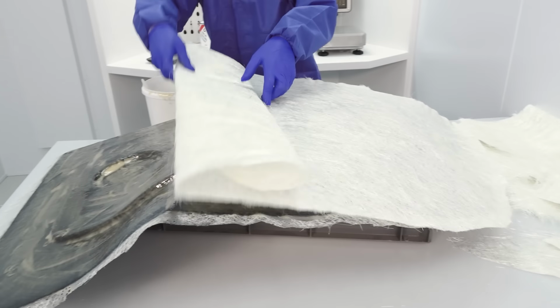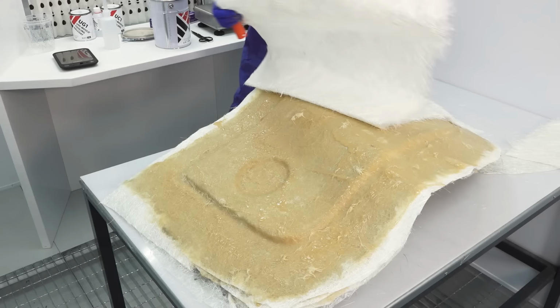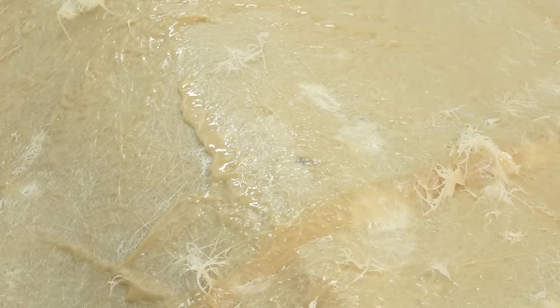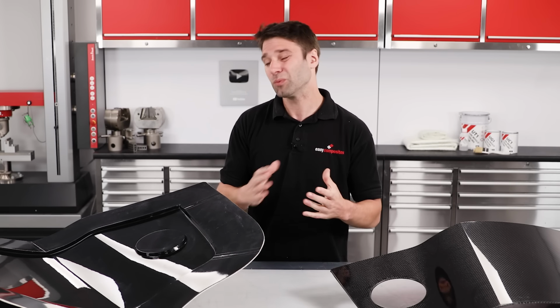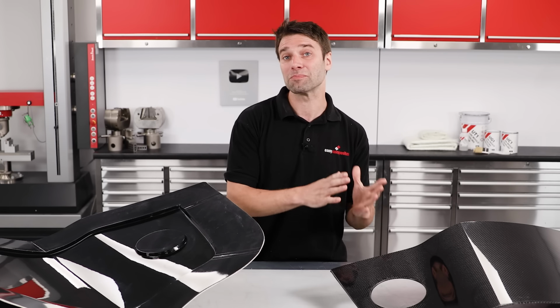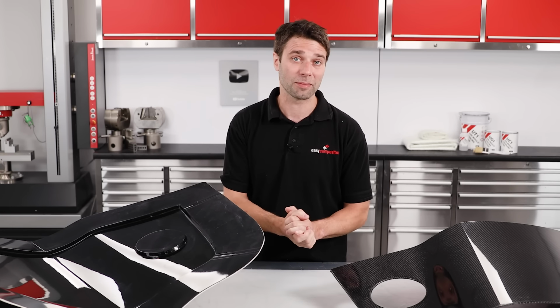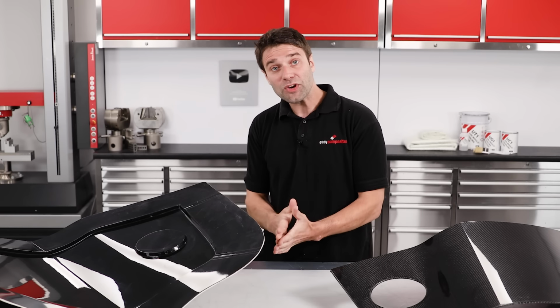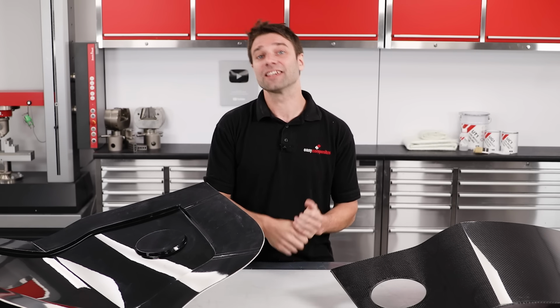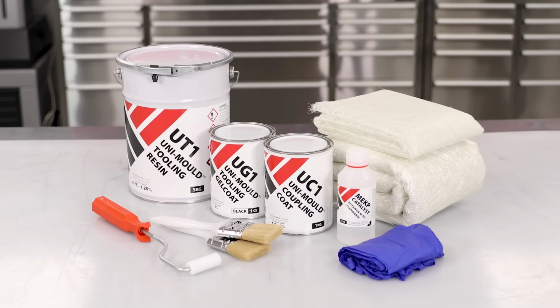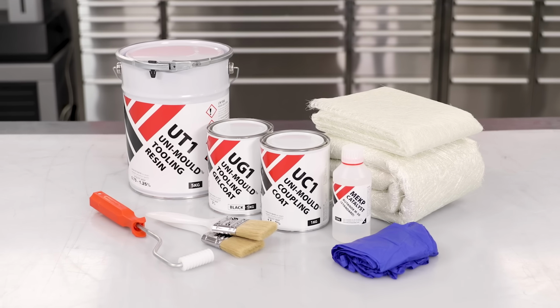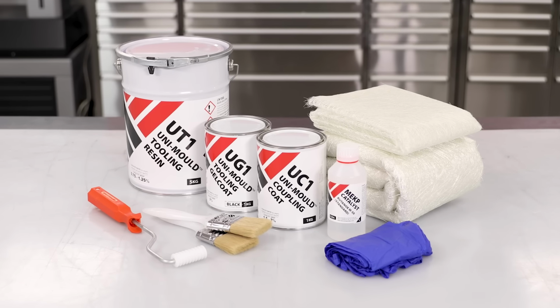Following this, 4 plies of chop strand mat are applied in one go using a special filled resin that cures with minimal shrinkage and distortion, which, as you may know, can often be problematic with traditional fiberglass resins. In summary then, Uni-Mould is a cost-effective and time-efficient mold making system that's often going to be the best choice for low and medium temperature processes.